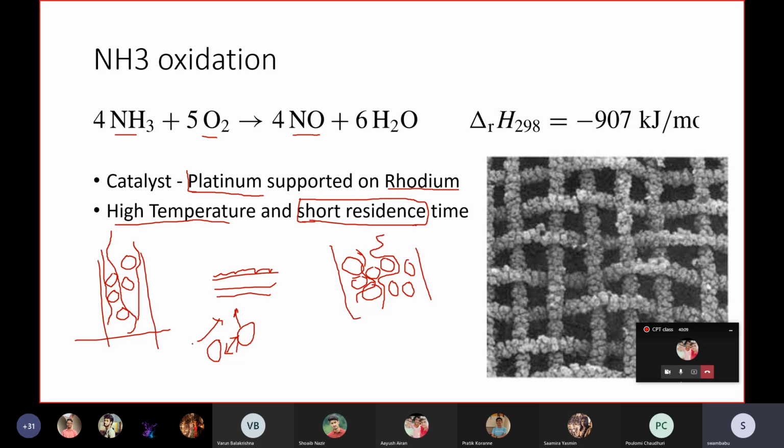When particles hit each other, what will happen? The layer of platinum usually comes off, because even though you coat it, it is not very strong. The interaction between platinum and any other metal is very little. So we can never cross-link the platinum; we can only simply coat a small layer. So in a fluidized bed reactor, because there is a high chance of attrition between the particles, there is a possibility of peeling off of the platinum on the surface. We cannot use fluidized bed reactors, and we cannot use packed bed reactors either.